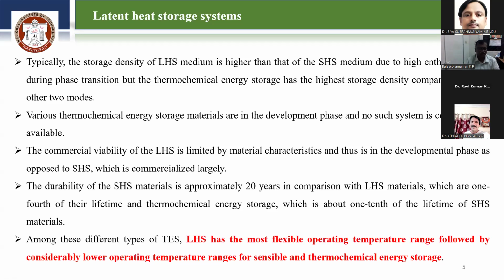However, this sensible heat storage is commercialized on a large scale. And when we discuss the durability of the sensible heat material, it is almost around 20 years, whereas the latent heat material is around 1/4 of that lifetime. And when we compare the thermochemical energy storage, it is about 1/10 of the lifetime of the sensible heat storage material. So the lifetime is very low for the thermochemical energy storage, and similarly for the LHS materials.